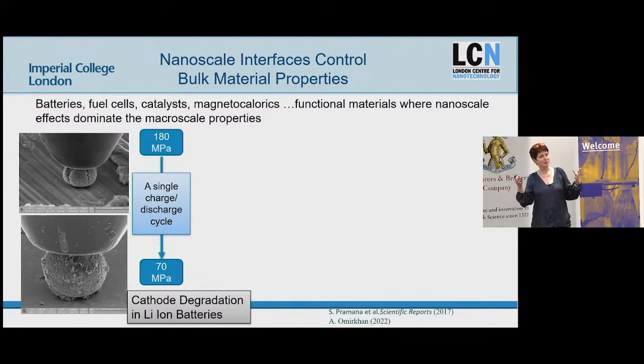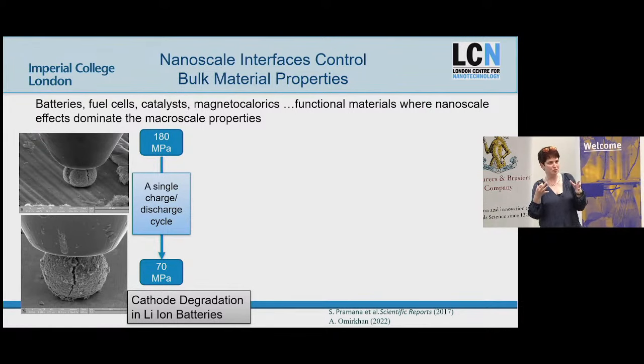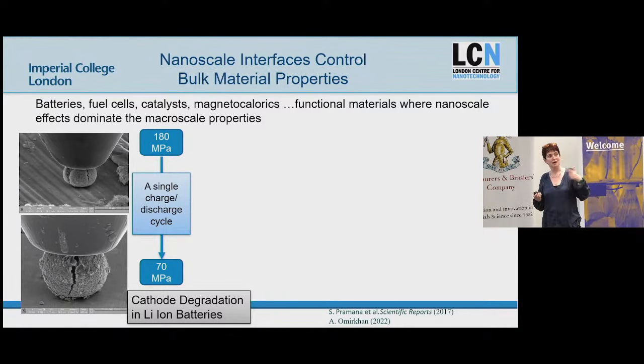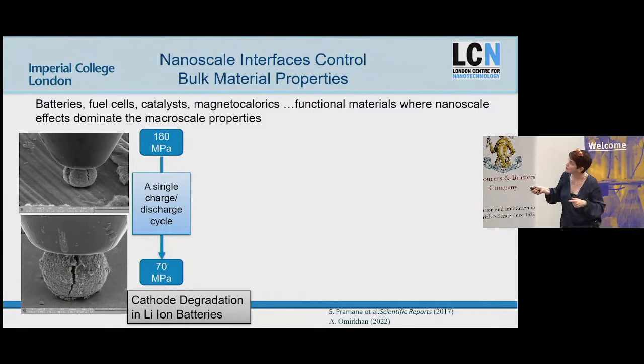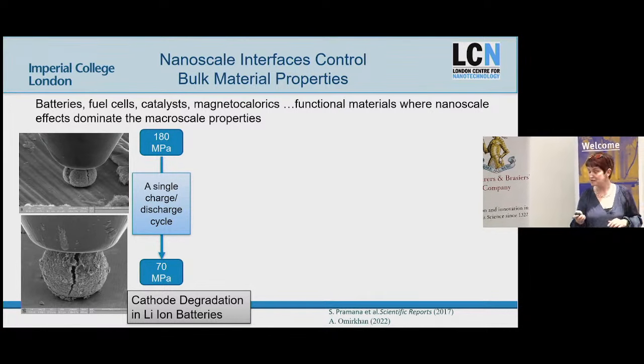So now you're thinking about cycling that for tens, hundreds of thousands of cycles, and the mechanical properties being critical to whether it cracks or is stable. These nanoscale interfaces, where the ions are moving in and out, are being weakened by that process. Right? And you can see, if you look carefully, the pathway of this is along those nanoscale intergranular sites.